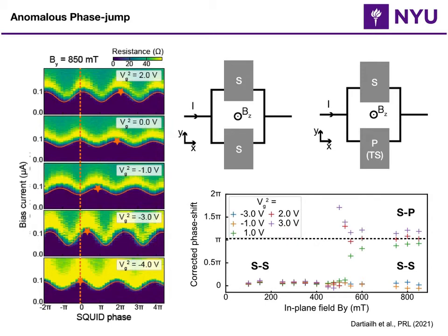And we now have three different signatures and proofs. One is that we see the gap closing and opening, supercurrent closing and opening, in our measurement. Another is that it is highly dependent on field direction, and it only works with the spin orbit direction that is described by the theory. And we also measure the phase while we do this transition, and the value is around pi. So this is all great.